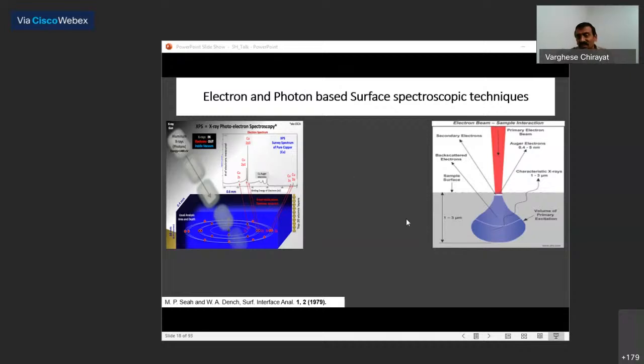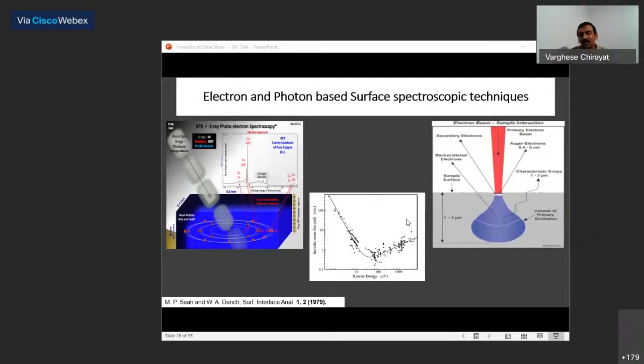So the surface sensitivity of both XPS and electron-based electron spectroscopy is not based on the probe. It's not the probe which gives you the surface sensitivity, because the probe goes deep. What determines the surface sensitivity is something called the inelastic mean free path of the electron which is trying to come out.